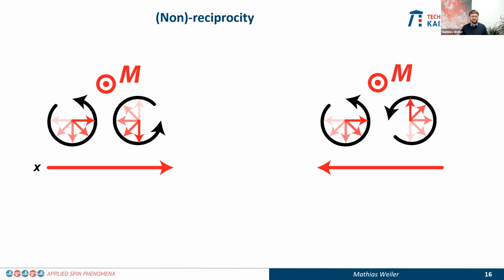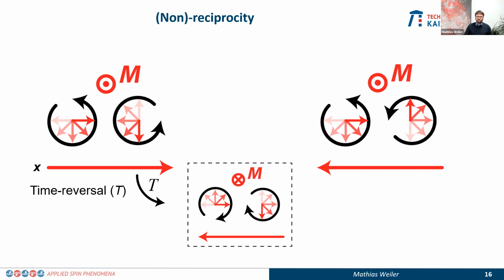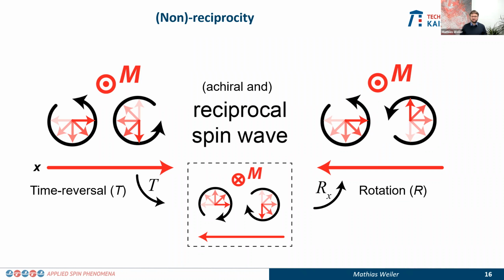Now, going back to spin waves, if you look at a spin wave over here, and we want to map this spin wave to its counter-propagating part, then what is different about the spin wave is that the helicity of the precession, which here in this case is counterclockwise, is set by the direction of the magnetization and not by the propagation direction of the wave. Well, that means to obtain the counter-propagating wave, we have to do a time reversal operator. That will mean that all the spins rotate in the opposite direction, like that. And then we still have to do a rotation. And then we recover this wave over here. So we rotate the entire picture like that. And that means such a spin wave is not chiral. There's no surface in this wave. It's a bulk spin wave. And it is also reciprocal.